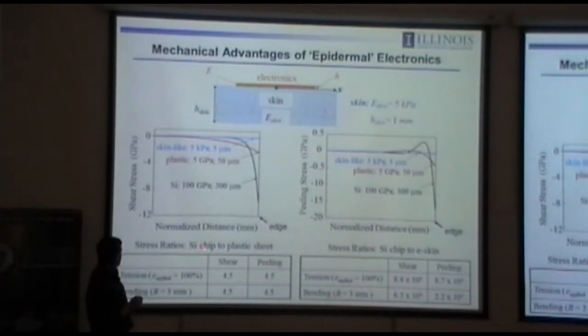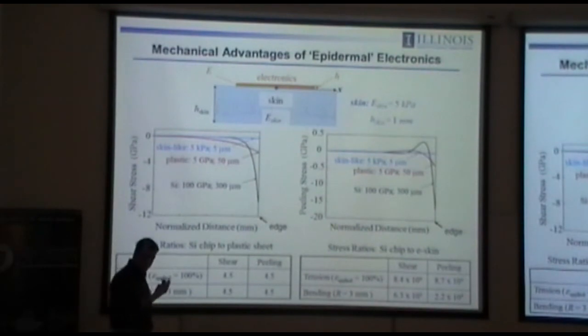Think about the ratios. Think about the ratios of silicon chip to plastic sheet for two cases. One is you pull the skin in tension up to 100%, and the other is that you bend the surface of the skin to a radius of curvature of 3 millimeters. And you compute the peak stresses for silicon chip to plastic sheet and compare the case for shear and peeling. And remarkably, the ratios are almost all the same in these four cases for chip to plastic sheet. And moving from chip to sheet helps, but only by about a factor of 5. So that might have some level of influence in the way you think about adhesion management, but not at a qualitative one, since it's just a factor of 5.